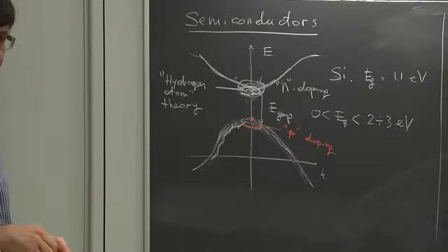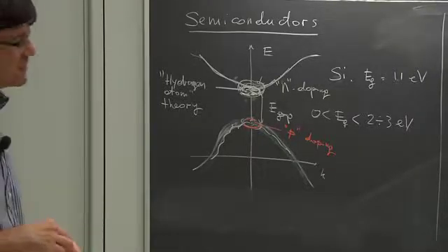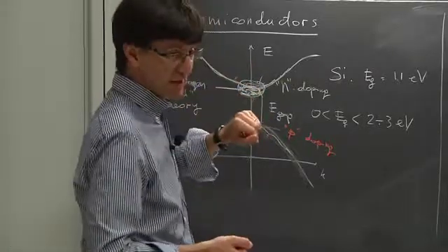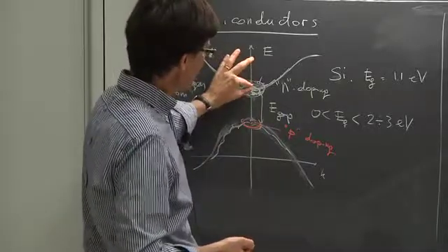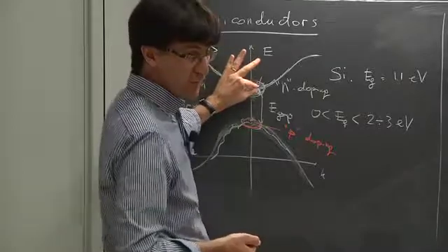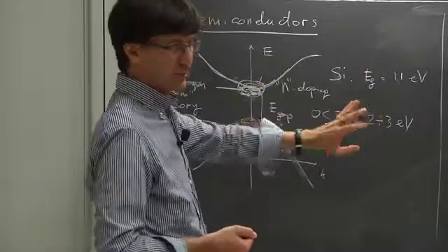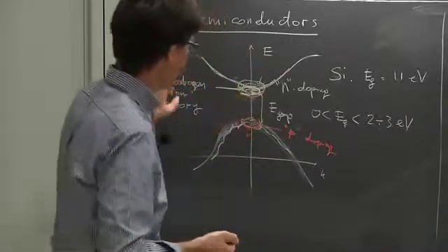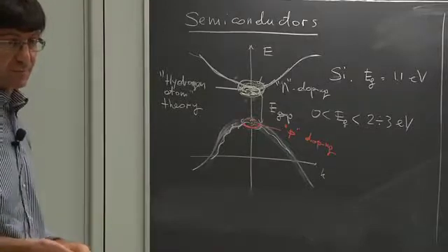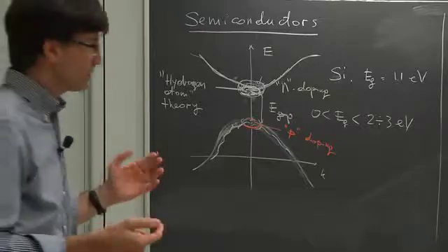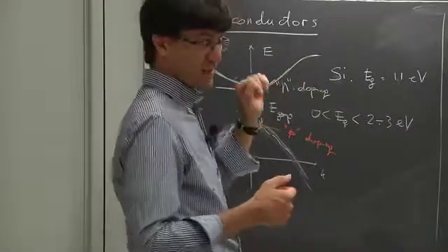Yes? When we introduce impurities, does it change the energy gap? By a little, because you're perturbing. The question is whether by introducing impurities you're changing the energy gap. You're changing it by an amount which is extremely small, and to be perturbation theory, it must be small. Otherwise, if it's too big, perturbation theory doesn't hold. So they change the band gap, but by a small amount, of the order of milli-electron volts. Compared to a value, say, of 1 electron volt, it's nothing. Temperature, for example, changes the value of the gap by a larger amount.